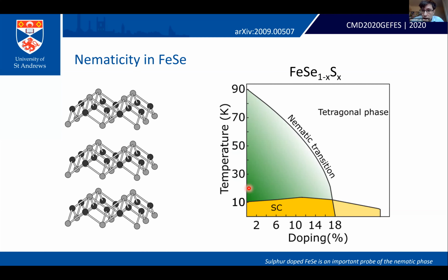Moreover, because sulfur is isovalent to selenium, you're not adding or removing any hole or electron carriers when you dope this material. You're simply applying a bit of chemical pressure, which has the effect of suppressing this nematic transition, whilst leaving the underlying electronic properties in the tetragonal state relatively unaffected. And so you can think of 18% iron selenium sulfur as having practically equivalent electronic properties to that of pure iron selenide at about 19 Kelvin. So over the years, a lot of experimental resources have gone into probing this phase diagram. And what I want to present today is a theory which can hopefully unify many of the unusual experimental results that we are observing.